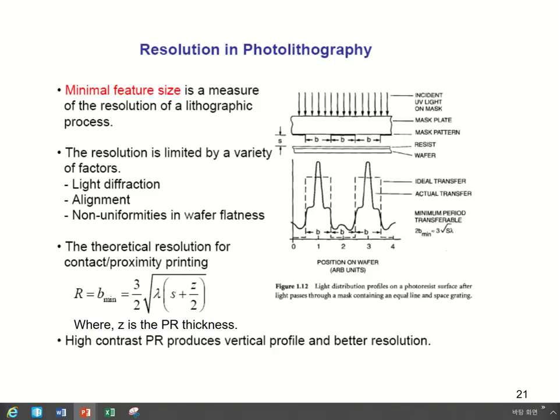Resolution is limited by a couple of factors. There is light diffraction through the mask, right? And there is also misalignment, which causes some problems for resolution. If there is already some pattern located on the wafer and you want to align the mask pattern with them, then small misalignment eventually causes errors, and that also reduces the resolution. So that's an important factor. And then the wafer flatness: a uniform wafer flatness is necessary to have a good overall resolution through the photolithography.